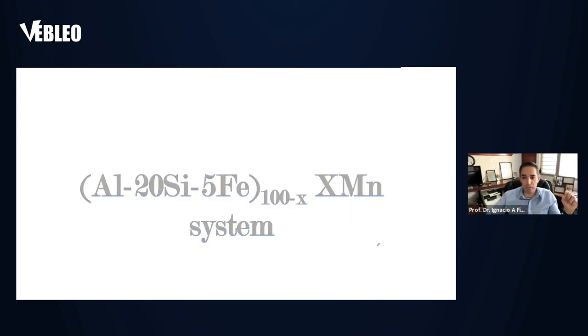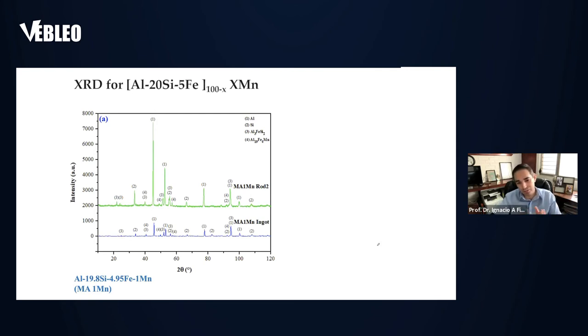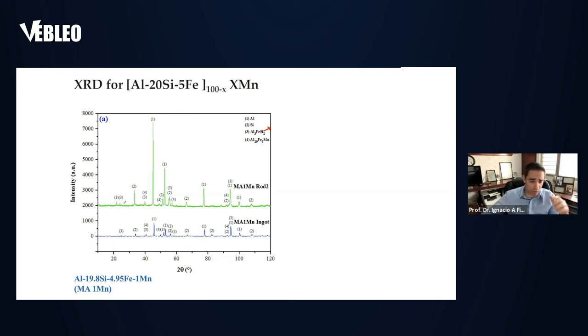Next I'm going to present the manganese effect in the master alloy system. For the manganese — also considered an impurity — we added 1%, 3%, or 5%. In terms of XRD with manganese we also got three or four phases: the one from the master alloy initially, and a second intermetallic we call the intermetallic with manganese. As we increase the cooling rate, the low-angle XRD peaks disappear — basically the phases from the master alloy disappear — and the intensity of the XRD peaks also drops.